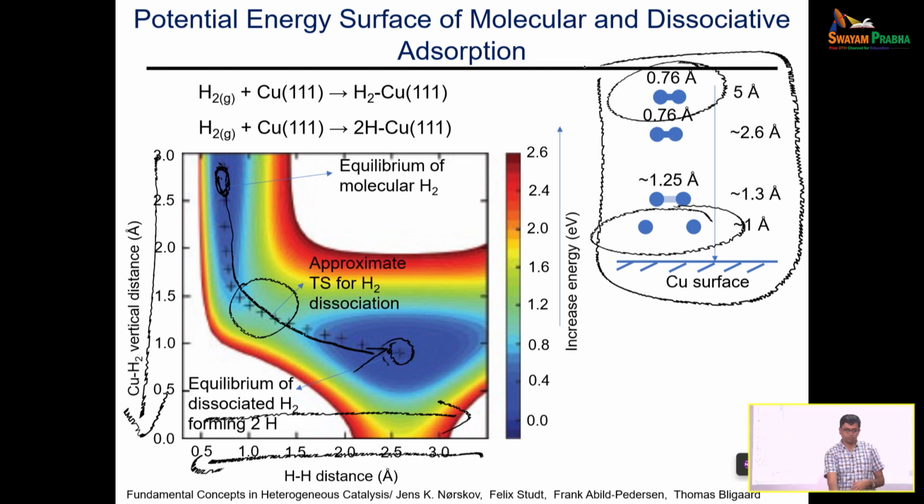In this case, in terms of energies, both of them are very similar, but we can capture the change, and what you see from this energy state, which is molecularly physisorbed, to this particular state, which is dissociatively adsorbed and chemisorbed, you have a rise in energy, and that particular rise in energy is what you need to be supplying for the molecule to be breaking.